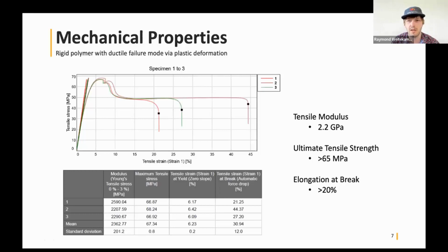Every now and then you'll get a dog bone at 100. At that point, once you're in that plastic deformation, there's a statistics game of when is that crack going to get big enough to pop the part. But this is really solid mechanical properties, where there's very good stress retention, but there's still flexibility. So maybe the snap fit buckle would be a good example, where it can deform enough to click into place, but it can also lock, right? That would maybe be a more visceral way of explaining what we're looking at on this curve.